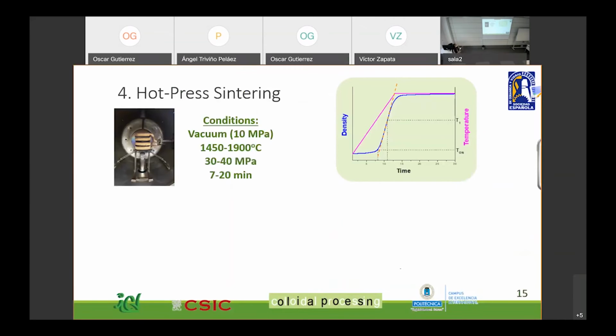Here we have the conditions we applied to sinter our samples, and to determine these conditions, we used the shrinkage criteria method. For example, here we have to look at some parameters like T on, which is the temperature at which the shrinkage of the sample starts, and T1, which would be the temperature at which the shrinkage rate is maximum. From that point, the slope of that curve would determine the maximum temperature at which the sintering process takes place. So heating stops at that point, and finally the sintering process would stop when the 100% theoretical density with densification of the sample takes place.